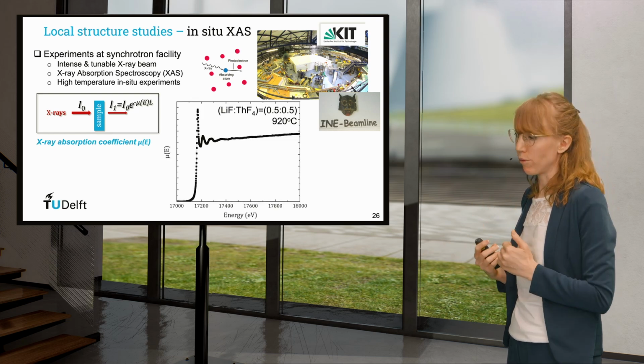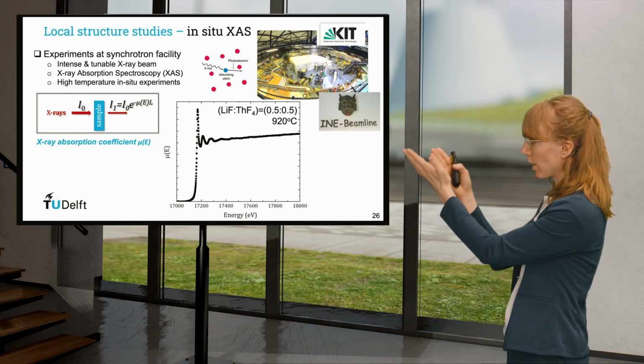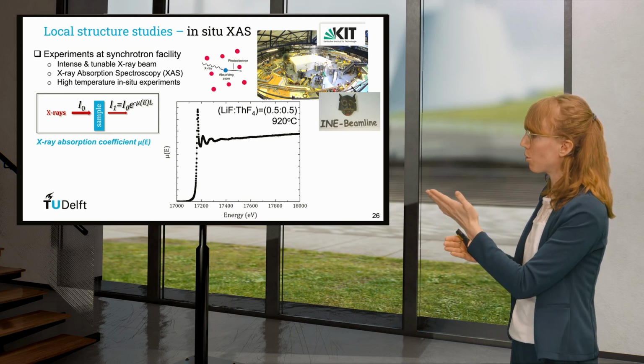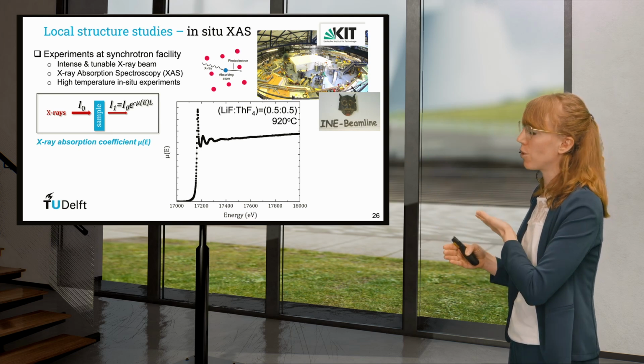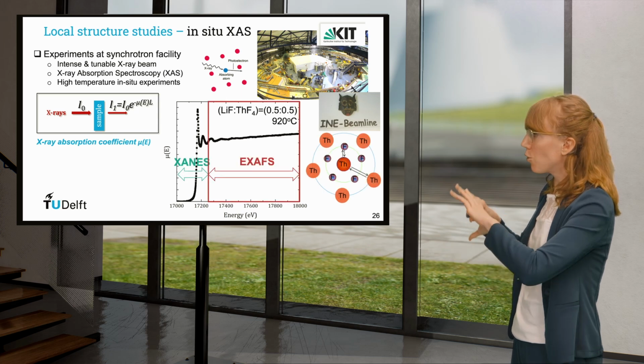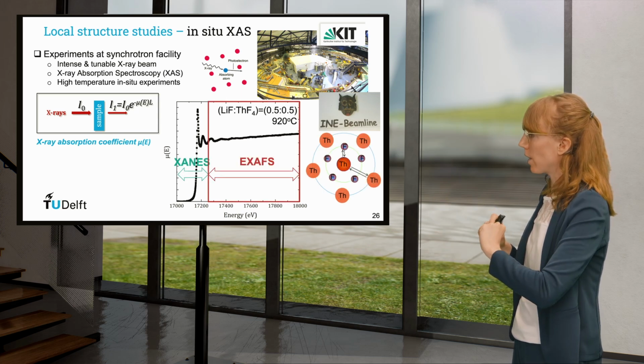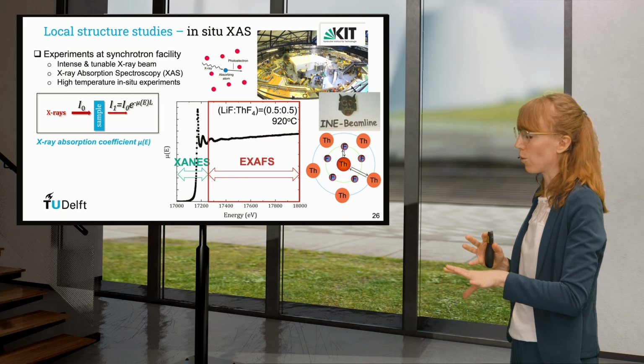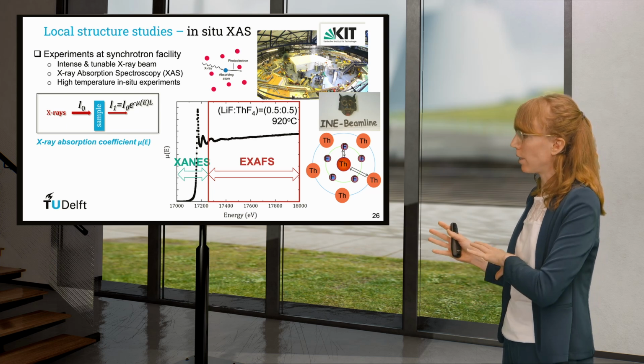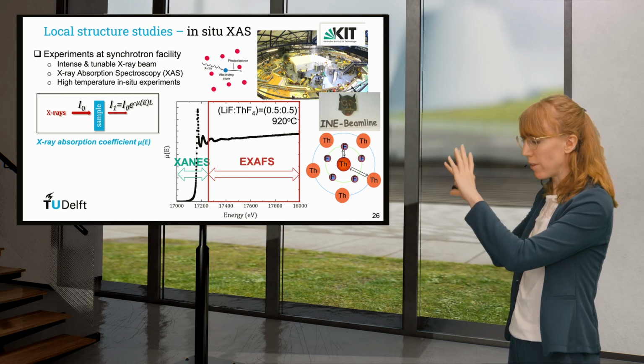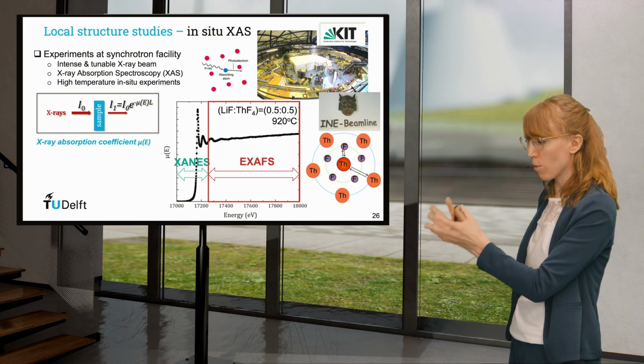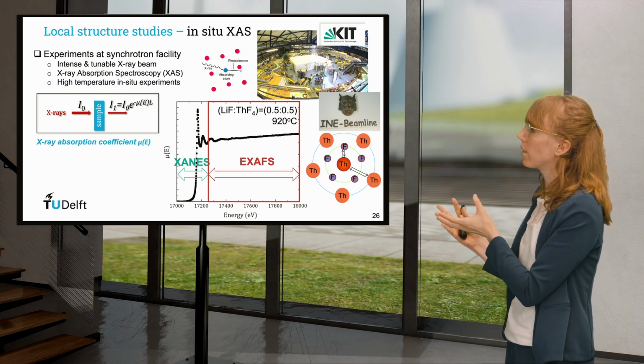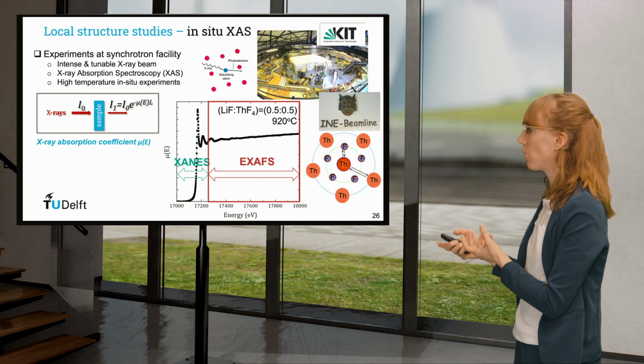So we perform such an experiment, and we get a figure like this one, which is the absorption coefficient as a function of energy. There are two regions in this figure: a low energy region called XANES, and a high energy region called EXAFS. It's the EXAFS I'm going to discuss. That's the one we are interested in to know more about local structure.